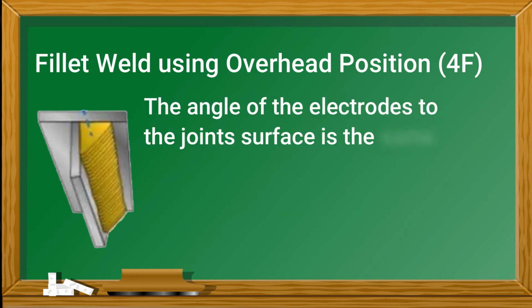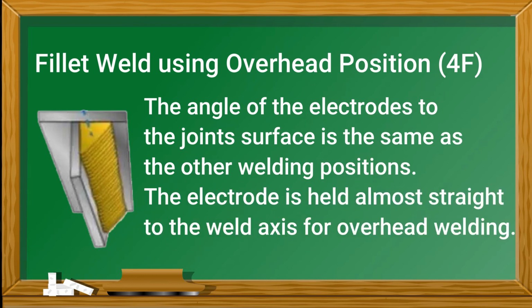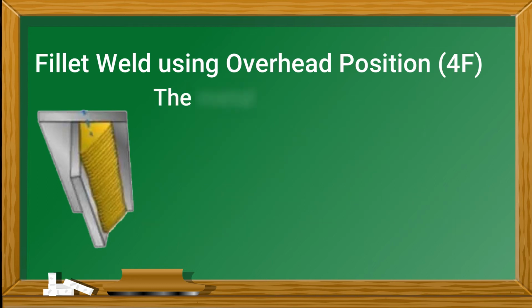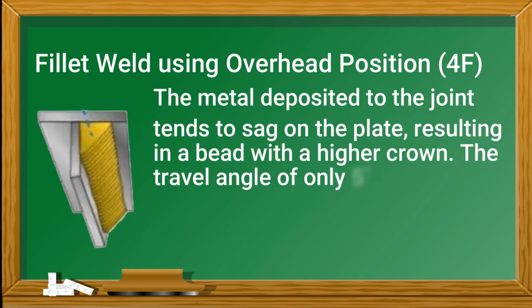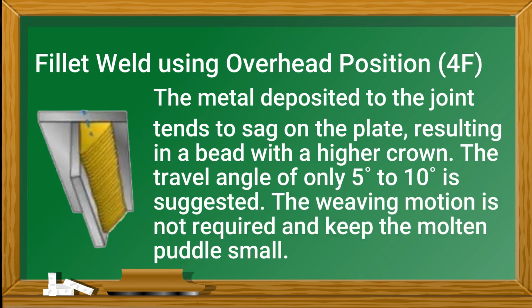The angle of the electrode to the joint surface is the same as in the other welding positions. The electrode is held almost straight to the weld axis for overhead welding. In this position, the metal deposited to the joint tends to sag on the plate, resulting in a bead with a higher crown. A travel angle of only 5 to 10 degrees is suggested. The weaving motion is not required, and keep the molten puddle small. If the weld puddle becomes too large, remove the flame for a moment in order to allow the molten metal to cool.